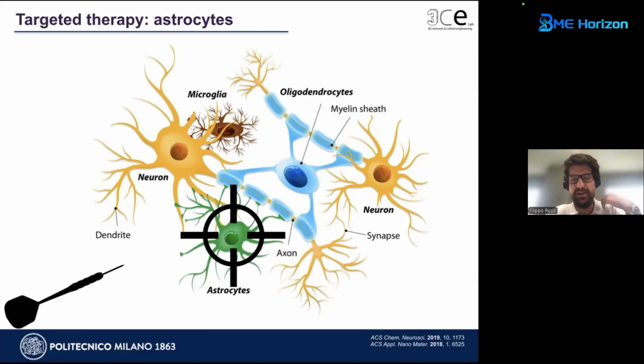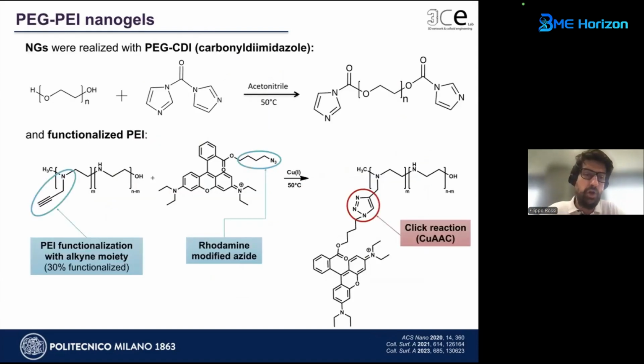The first one is that astrocytes present an extremely lower phagocytic activity with respect to microglia, and also when you have astrocytes, you also have microglia in the same environment. So these Trojan nanoparticles should reduce the amount taken up by microglia and move into astrocytes. Consider that microglia present an extremely higher phagocytic activity. So this is why this problem was extremely more difficult with respect to the previous one. It's commonly known in the literature, even if, as I told you, there is not a real coherence, something completely understood that every scientist agrees on, that microglia are more susceptible to polymeric micelles because they present hydrophobic domains, and we have to say that they recognize them more like foreign bodies with respect to other cells.